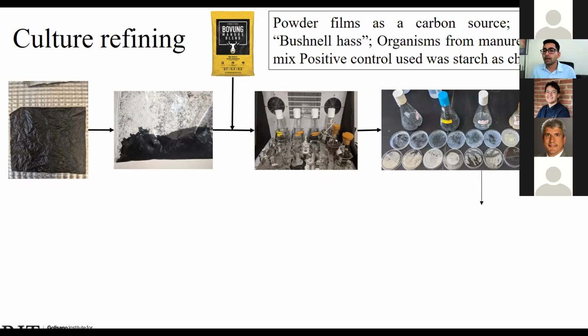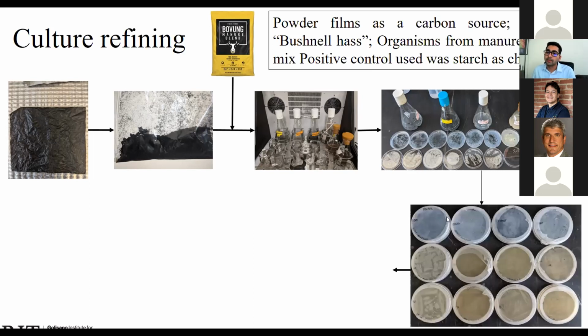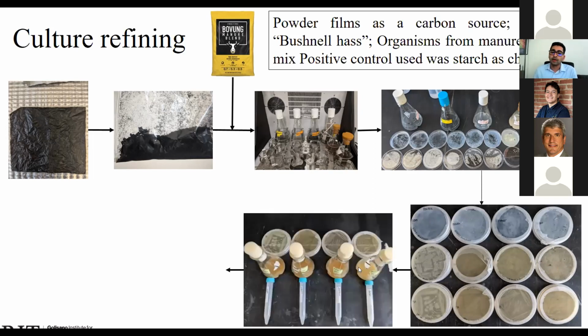Finally, after about 3 months or so, when we had our refined cultures ready, we incubated these on powdered plastic Bushnell-Haas media agar plates, and these are nothing but the same mineral media in an agar form, with the plastic powder sprinkled on the top. And we incubated these in duplicates for 7 days and 14 days, after which we isolate the cultures on a more generic media plate, which is the plate count agar, and refine our cultures. And here we have some mixed cultures as shown.